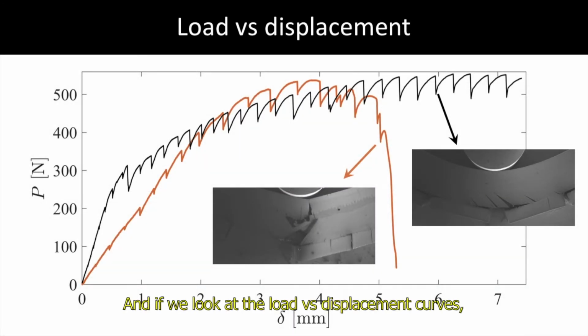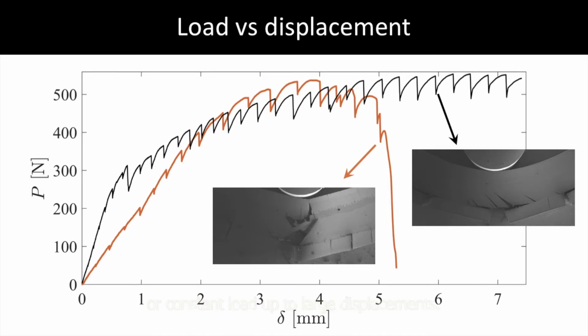And if we look at the load displacement curves, all the load drops are caused by specimen relaxation while we pause the test to take SEM images. We can see that both microstructures dissipate energy under stable conditions, even more so the bonded specimen that dissipates energy under increasing or constant load up to large displacements.